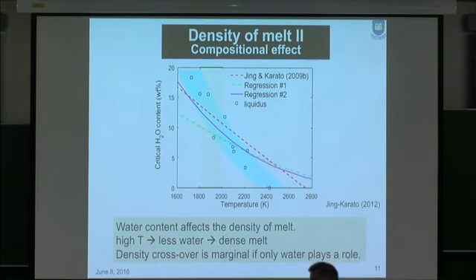Iron tends to go to the melt under these conditions, makes melt dense, but because of the very fact that melting in the deep mantle occurs only because of the presence of volatiles, volatiles do go into the melt to make melt density lighter. So there's a very delicate balance between the iron effect and the volatile effect. We spent some time in my lab to find out the competition. Briefly, there is very strong competition between iron and water, and as a consequence, the melt tends to be dense when partial melting occurs in the deep mantle at relatively high temperature conditions in the general environment.